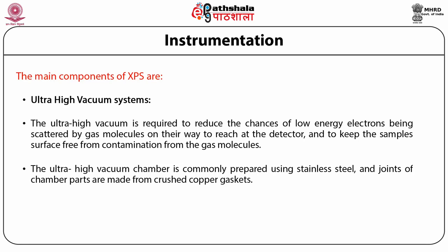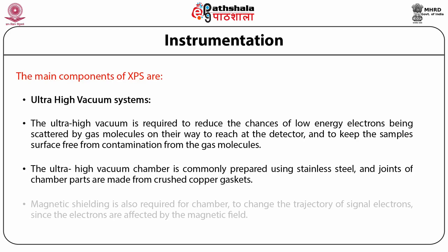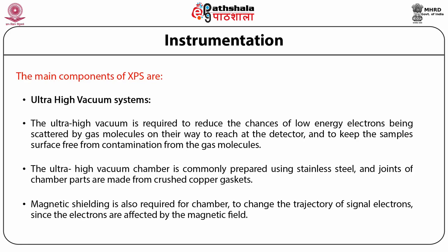The ultra high vacuum is required to reduce the chances of low energy electrons being scattered by gas molecules on their way to reach the detector, and to keep the sample's surface free from contamination from the gas molecules. Low energy photoelectrons and Auger electrons are easily scattered by the gas molecules. Scattering reduces the signal intensity and increases background noise in the spectra.